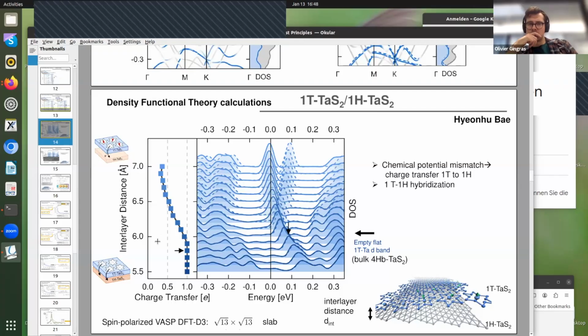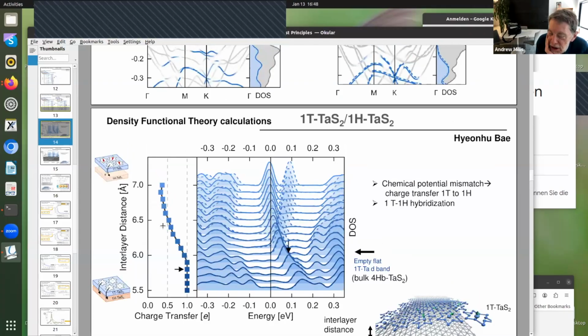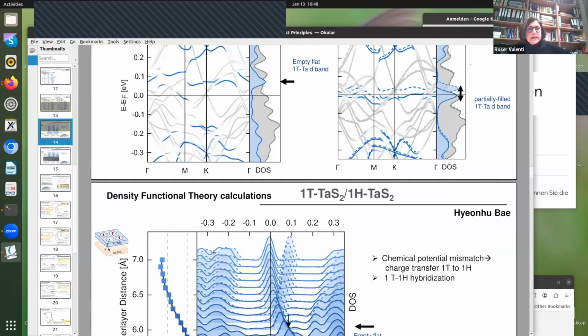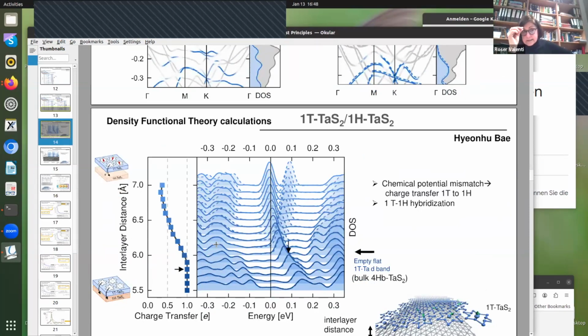Andy? Hi. Thank you. I realize I missed one other point. When you consider the case of substantial charge transfer between the layers, does the Star of David lattice distortion change? Or is that kept fixed? Well, indeed, in this calculation at the DFT level, the relaxation was done allowing also for what happens to the charge, and the changes are very small. So in fact the Star of David remains very robust, even if you have some doping, some charge transfer. Interesting. At the level of the DFT, it's pretty robust.